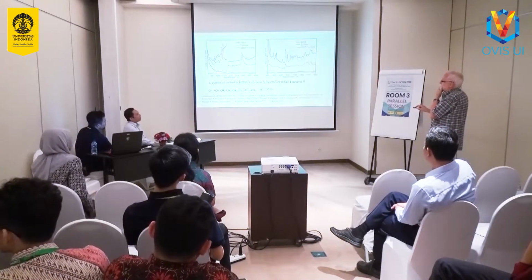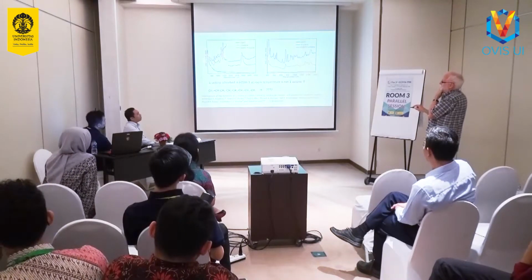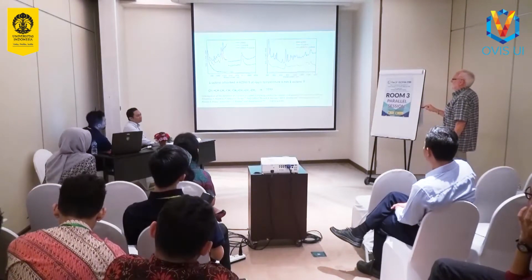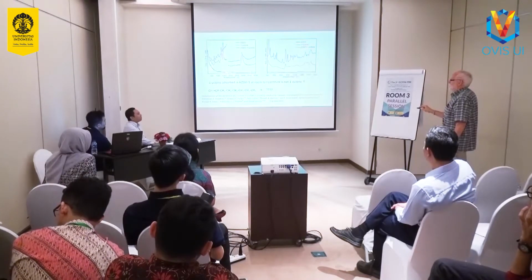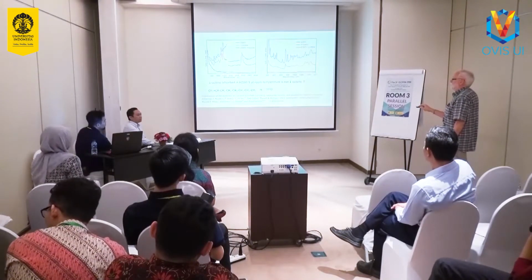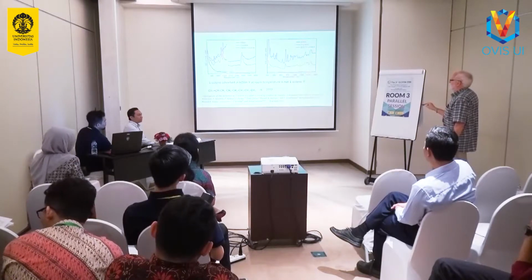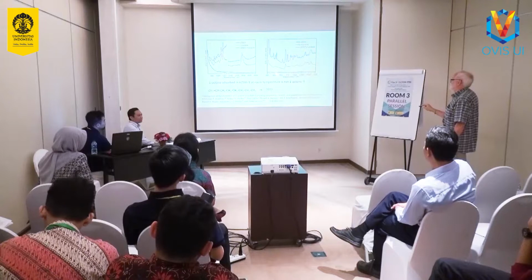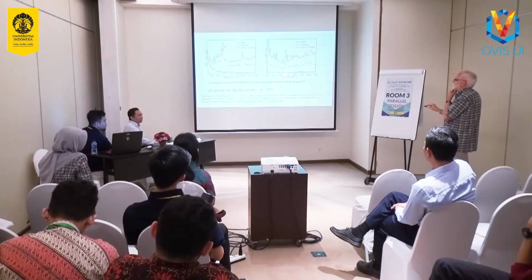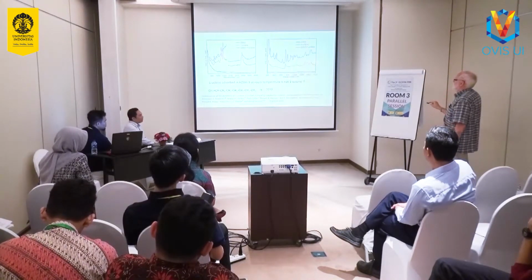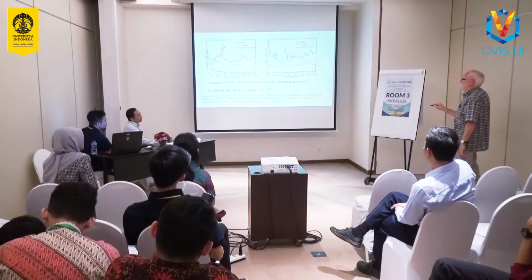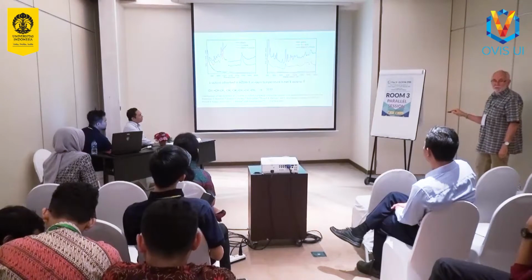Here's the spectrum. This is now inelastic neutron scattering, so vibrational spectra again. Here's the spectrum of the blank zeolite. There's the OH groups. Again, very clean spectrum. With this spectrometer, we can see all the way down to 200 wavenumbers very clearly. There's almost nothing there. If we absorb 1-octene in the zeolite, that's the red spectrum, then of course we see all the vibrations of the 1-octene, which contain hydrogen. That's most of them.